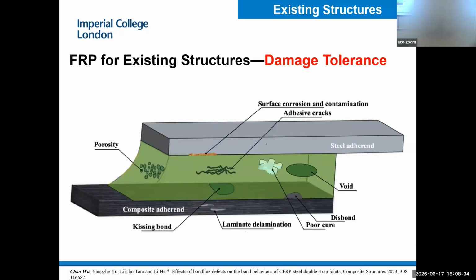We focus a lot on the interface. If you want to use this material for structure strengthening or repair, you always have technicians on site. You install the material on the surface, brush it with glue, then attach the material. You cannot promise 100% good quality of installation. You always introduce defects to the bond line, like porosity, air voids in the glue, kissing bonds, inclusions, and micro cracks. The bond line is never perfect.